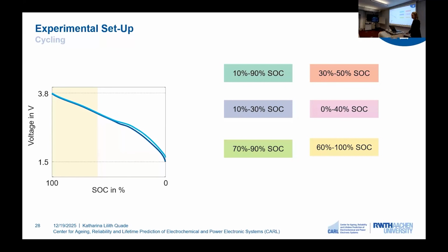60% to 100%. And now, for every category, we cycle several cells because of the lower maturity level of the sodium-ion batteries. And we can even see that for the first condition here, we cycle 40 cells because we initially assumed that this was the category with the most aging.